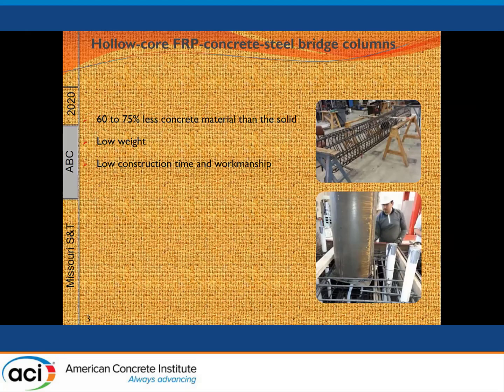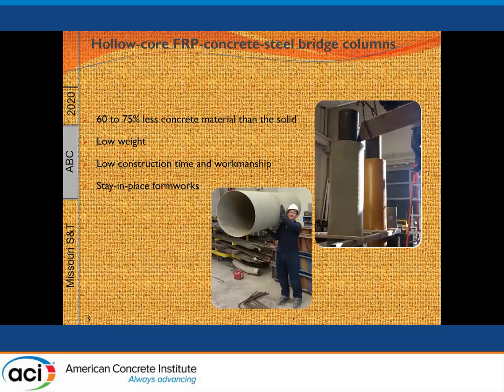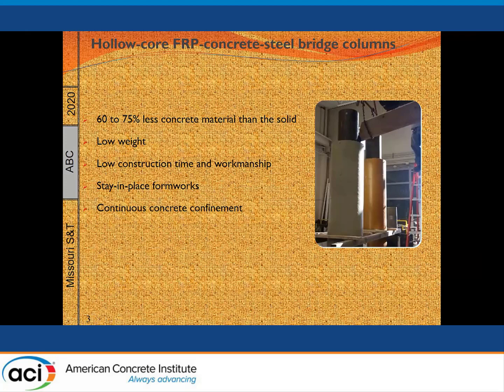Here's just a steel tube fixed on the cage during the construction. As I mentioned, those would be stay-in-place formwork. So if you are adapting the cast in place, we have the steel tube inside, and then you have the glass fiber outside, and then we fill in between the two pipes with the concrete. Concrete cannot escape anywhere. Concrete has a full confinement from inside with the steel pipe, from outside with the fiber reinforced polymer tube. You get a continuous flexure and shear reinforcement by the steel tube. Higher durability.